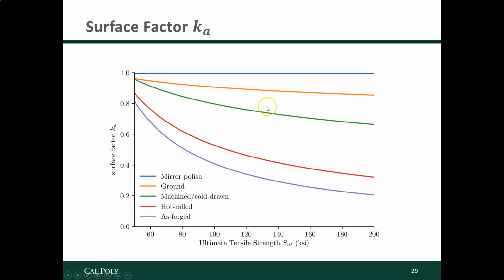If you have even worse conditions in your steel, if it's just machined, say like on the lathe, or if it's been cold drawn, if it's hot rolled, even lower. If it's just forged, then it's even worse, right? And so if you've got these really strong steels and the surface finish is really poor, you could end up with only 20% of the endurance limit that that same steel would have if it had a perfectly polished finish. So it's really important, if you need a good fatigue strength for your part, to make sure that the surface of the part is nice and shiny, because any imperfections from your manufacturing process cause cracks, and those cracks grow over time when it's subject to load, and that's what you want to avoid.